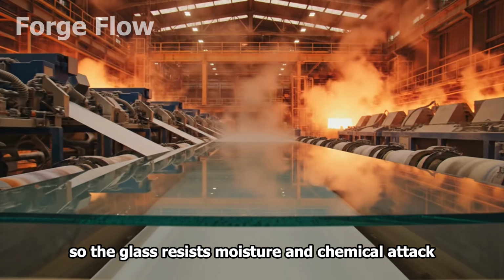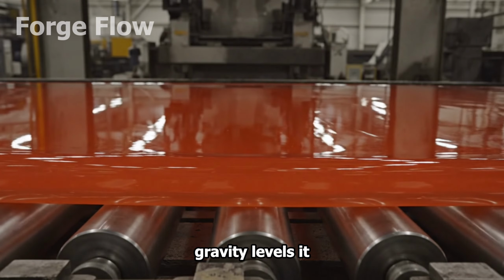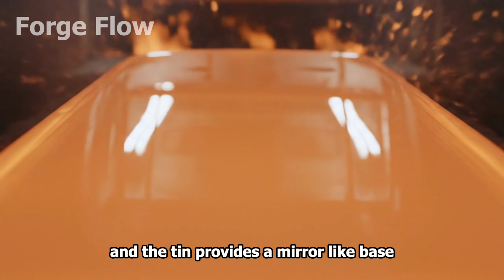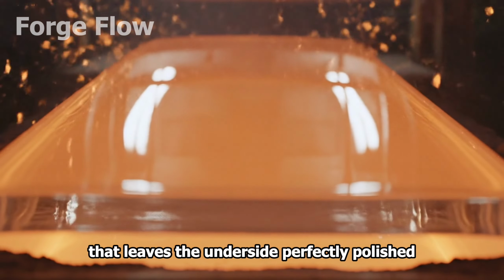Inside, a bath of molten tin waits below, protected by an atmosphere of nitrogen and hydrogen, so the tin surface stays clean and does not oxidize. Because tin is far denser than glass, the molten glass naturally spreads across it, floating like oil on water and forming a continuous ribbon. Surface tension pulls the ribbon smooth, gravity levels it, and the tin provides a mirror-like base that leaves the underside perfectly polished.